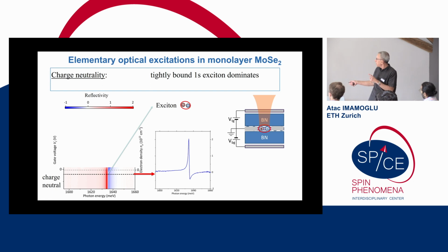Here, actually, this is relatively modest, so the peak reflection is twice as large as the background. In principle, these materials are atomically thin mirrors at the exciton resonance, so their reflectivity can be 85%. And if you suppress background reflection, this signal could have a magnitude of 40. Okay, so in that sense, doing spectroscopy by looking at excitons is relatively easy.